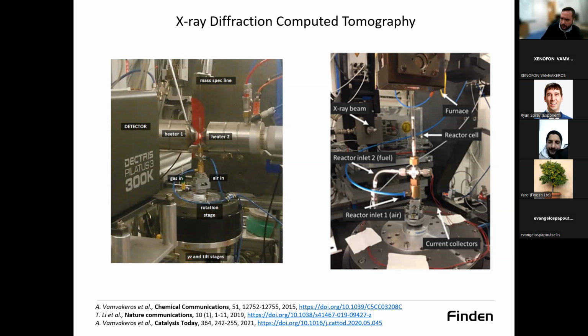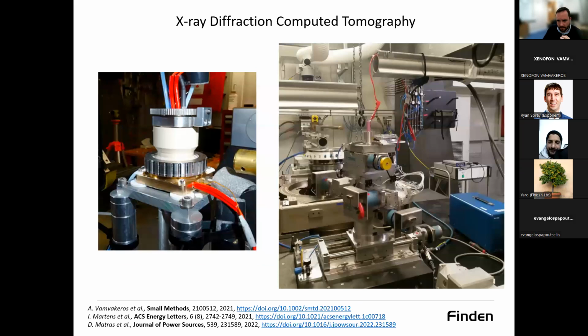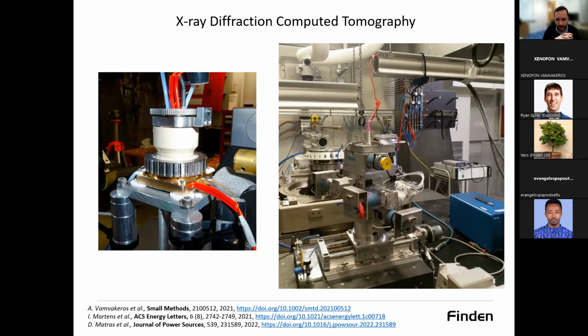On the right-hand side, you see an experiment. We used a solid oxide fuel cell, but the point here is that you can also use a potentiostat in conjunction with this type of experiment. A PEM fuel cell on the left, so you can go from, as we said, a small capillary to a real device, and on the right-hand side you can see an 18650 lithium-ion battery, and this was the first dynamic XRD-CT experiment